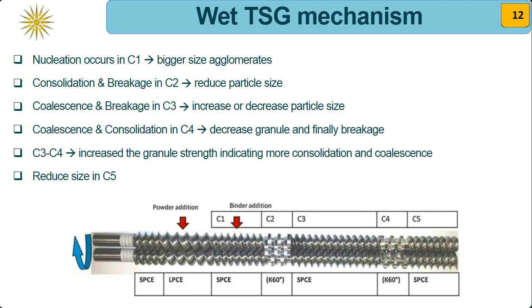The wet granulation mechanism was further studied by a group of researchers, where they split a granulator in 5 different sections. The powder addition was done in the beginning, where they used a large pitch conveying screw element, and later on in compartment C1 they used small pitch conveying elements to avoid back feeding of the material. They observed that the nucleation occurs in the C1 compartment where we have bigger size agglomerates, and as we move to section C2, which is the first kneading zone, we had consolidation and breakage.